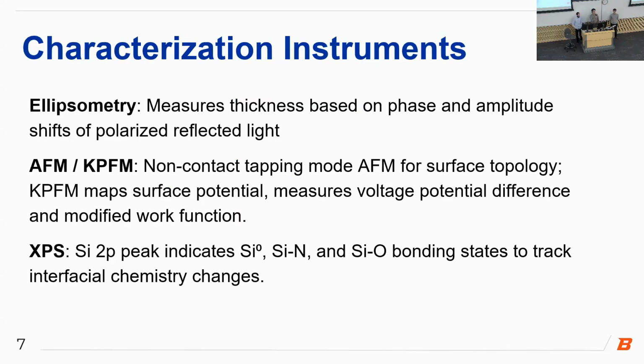So we use several instruments to characterize our initial films. First, using ellipsometry, which measures the thickness based on phase and amplitude shifts of polarized reflected light. This can be fit to a model, giving angstrom level precision, and is also non-destructive. We use non-contact tapping mode AFM for surface topology, and we use KPFM to map surface potential, voltage potential difference, and modified work function. This tells us if there's charges trapped in the film or not. Finally, we used XPS to distinguish the silicon 2p peak, indicating elemental silicon, silicon nitride, and silicon oxide bonding states to track interfacial chemistry changes.